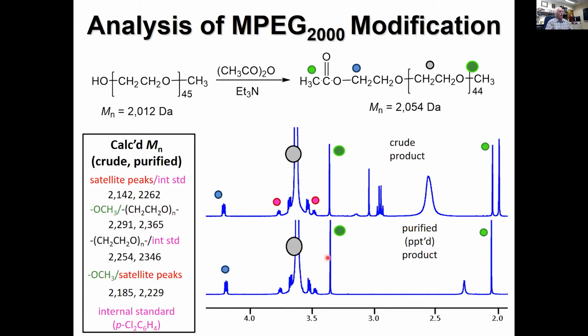This is a little bit of water. This is the CH3 of the ester group, this one here. This is the OCH3. And then we still have these satellites. So we can integrate this relative to the satellite to see how well the functionalization worked. We can also have an internal standard, integrate it relative to this, or of course to these N groups, and again we get these same sorts of molecular weights.